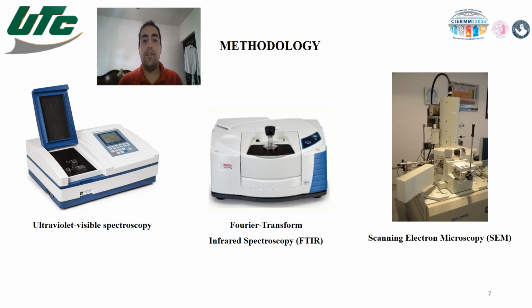This analysis was conducted using a Nicolet iS50 infrared spectrophotometer from Thermo Scientific, employing the ATR mode with 32 scans over a wave number range of 4,000 to 400 inverse centimeters. Finally, the third characterization is scanning electron microscopy, or SEM. The surface morphology and nanoparticle size of nanocurcumin was determined using scanning electron microscopy, employing a high-resolution HR-SEM microscope brand Auriga.